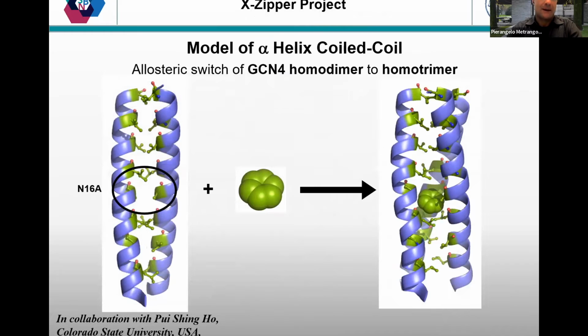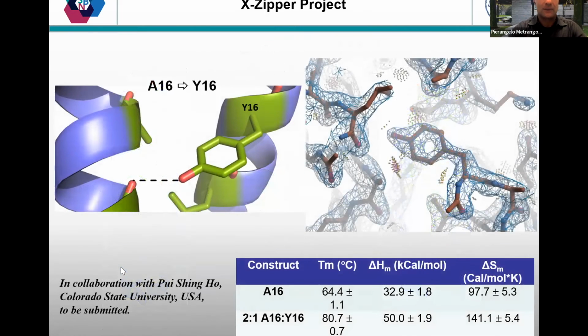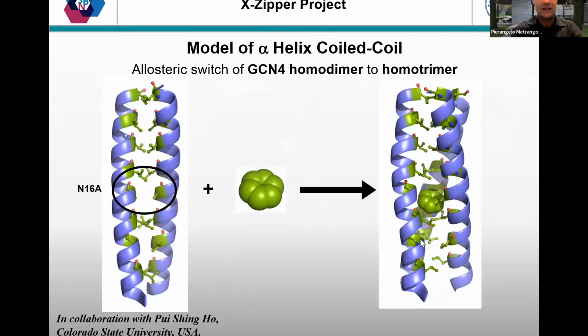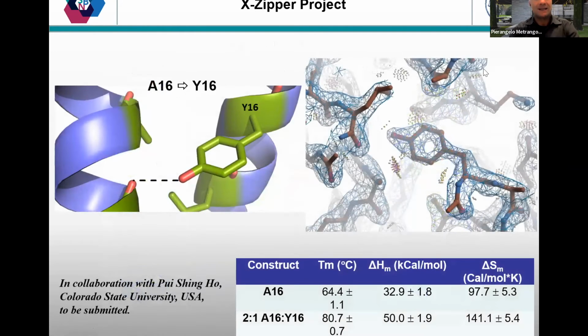Moving from beta sheets to alpha helices, we wanted to use halogen bonding to make peptide self-assembly. We got this 32 amino acid alpha helix, where we could replace an alanine in position 16 with tyrosine. Tyrosine makes a hydrogen bond here, promoting the self-assembly from a dimer into a trimer. So it is possible, by introducing a hydrogen bond donor, to convert a self-assembling dimer into a trimer. We made it with tyrosine, but we wanted to make it also with halogen bonds.